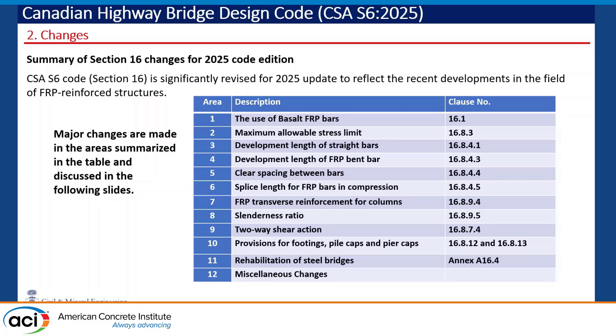The maximum allowable sustained stress limit has been raised from 0.25 to 0.30 of the ultimate. Keeping in mind that the strength of the bars has been going up from 600 to 800 to 1000 to 1200 and now 1400 MPa, that change from 0.25 to 0.30 seems quite significant.